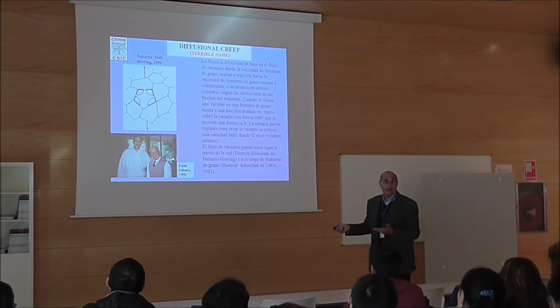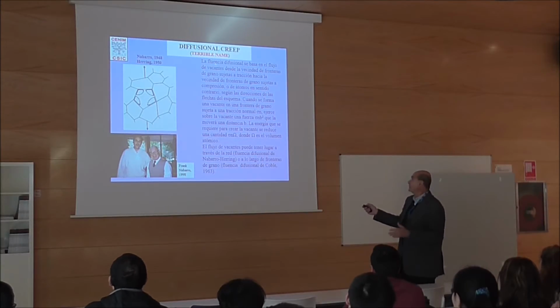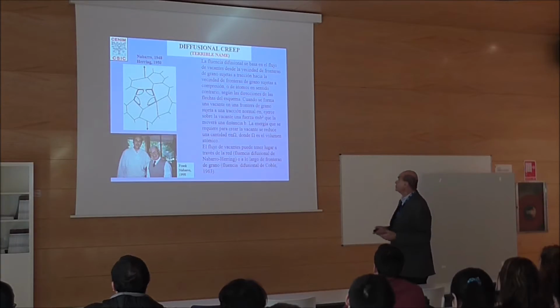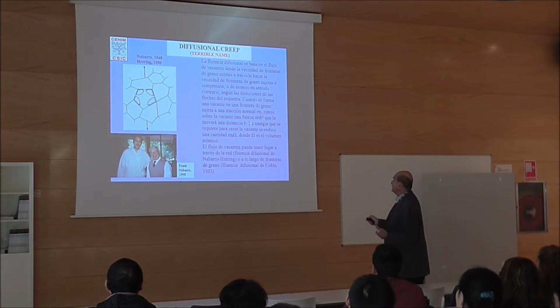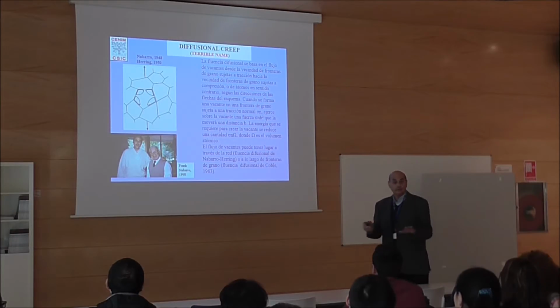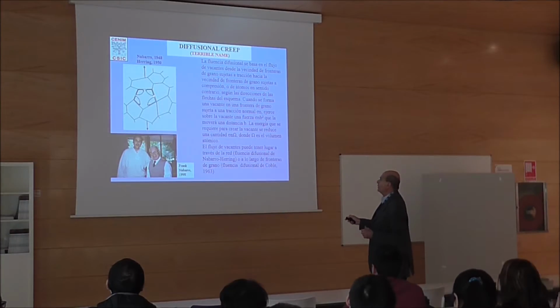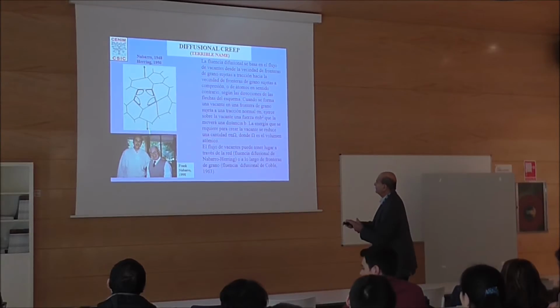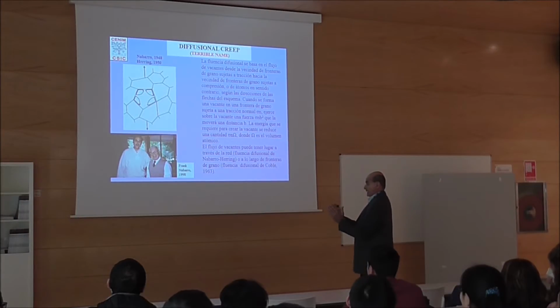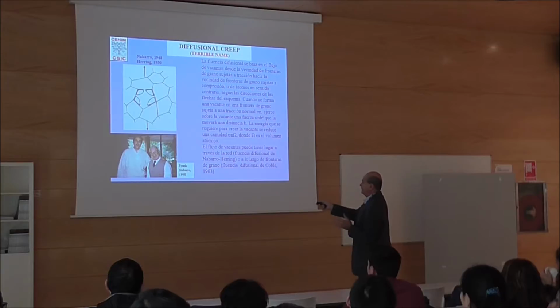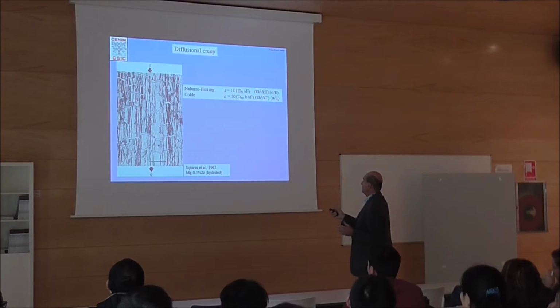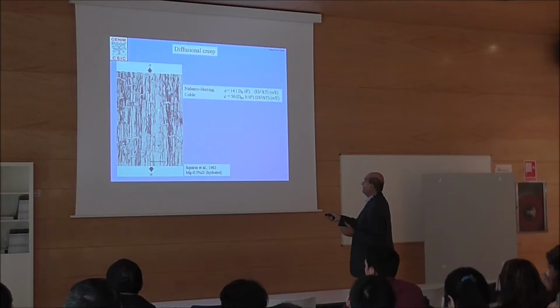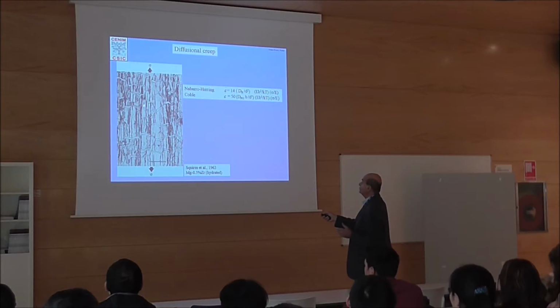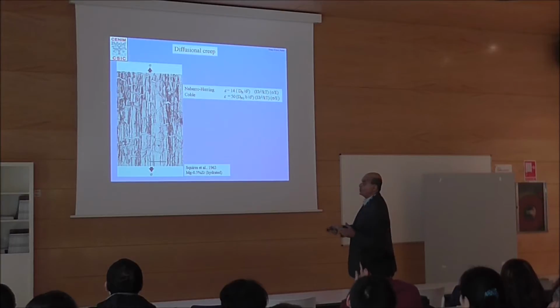I used to call that Nabarro-Herring or Nabarro creep, which is more proper to differentiate, because, as I mentioned, everything depends on diffusion. I'm not going to go into details, but this has nothing to do with dislocation, just a diffusion of vacancies from this type of region. This is the stress, this is tension. There is a component here that is pressing the atoms in the inverse sense. It's pressing the atoms in here, and the atoms will flow here, you will have an elongation, and these are called denuded zones.